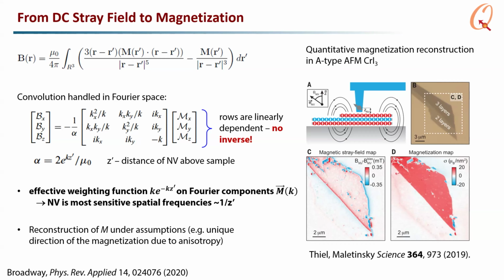So if you're 50 nanometers away from the sample, you're not really going to sense uniform magnetizations that are much longer than that, just because inside of a ferromagnet the magnetization is actually 0. The magnetization is highest on the edges of the ferromagnet. And then you're also not going to sense Fourier components that oscillate much faster than how far you are from the sample. Okay, but people can apply assumptions and reconstruct the magnetization.